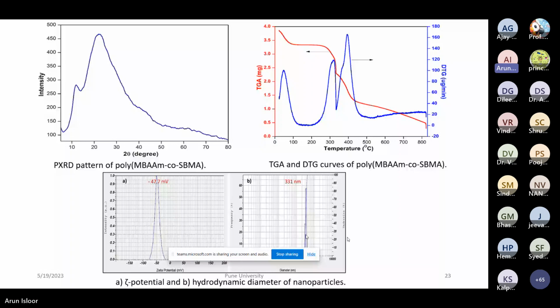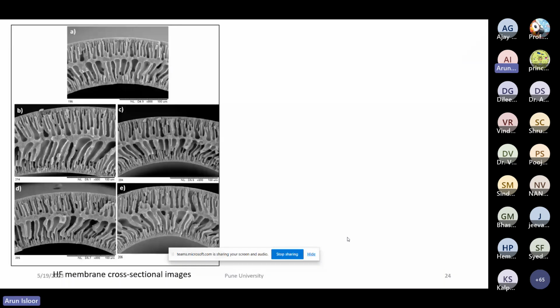Then of course these were incorporated into the polymer matrix, and the hollow fiber membranes were fabricated using this particular material as an additive. And you can see here the long elongated finger-like projections, which are nothing but the micro voids, through which the percolation or the separation of the fluid and the unwanted component actually takes place.